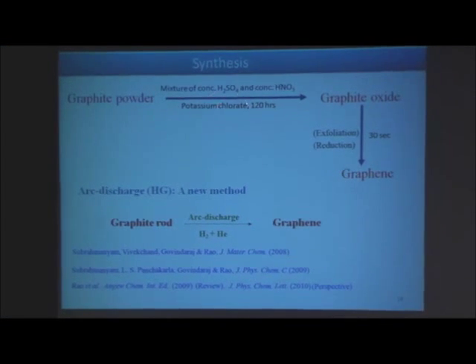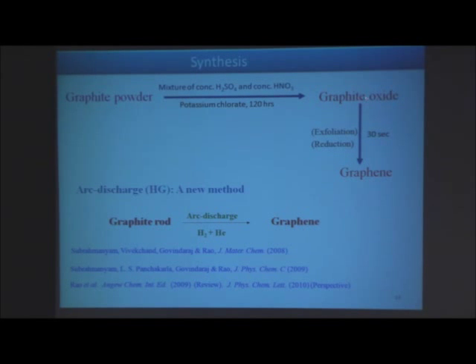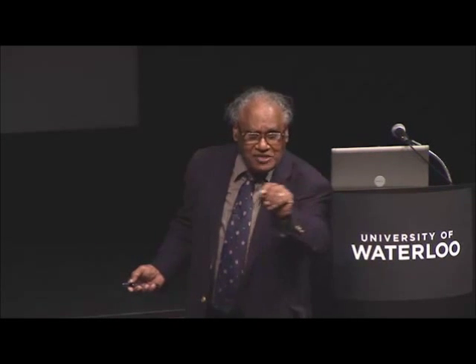Lot of methods. The simplest and the most important method that people use is the chemical method. Take graphite powder, cook it in an acid with an oxidizing agent, make graphite oxide. And graphite oxide can be very easily exfoliated by thermal shock or mechanical sonication. And then you reduce that and you can get graphene. Of course, that will be in solution, but you can't take it as a solid. That is the problem. You can take the solution, put the solution on any substrate, you get a graphene layer. Okay? But you can't call it graphene, you see. It is actually reduced graphene oxide, because a few oxygen functionalities will still be on the surface. It is not pure graphene.